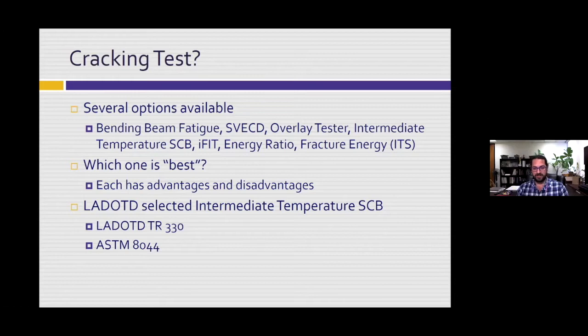Top-down cracking has a different mechanism than bottom-up cracking or low temperature cracking. So you have to look and see what type of cracking you have in your state, and then evaluate these test procedures and figure out which one gives you the most logical responses. If you have a lot of recycled content, then you would expect to see a reduced cracking resistance.